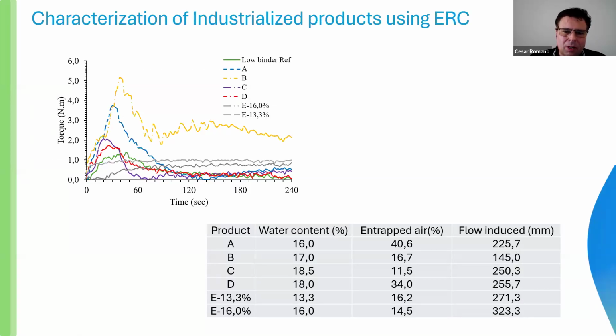For example, we used this same protocol to evaluate industrialized products here. And it was possible to observe that they have different concepts of dosage here. For example, these two products here presented after mixing a very high level of entrapped air. These two compositions here presented very considerable differences in the flow induced here.